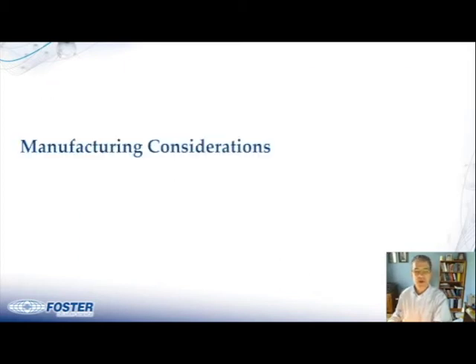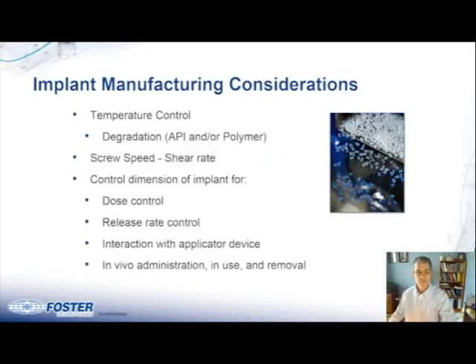So in this next part of the presentation, I will discuss some manufacturing considerations. There are several considerations for manufacturing drug polymer blends using melt extrusion, of which processing temperatures are perhaps foremost. Polymers process at specific temperatures which must be compatible with the active ingredient. A blend is not possible if the degradation temperature of the drug is below the processing temperature of the polymer.